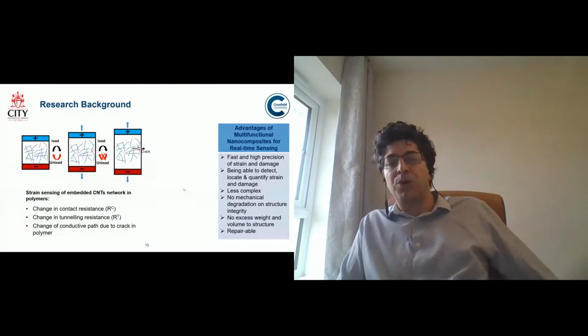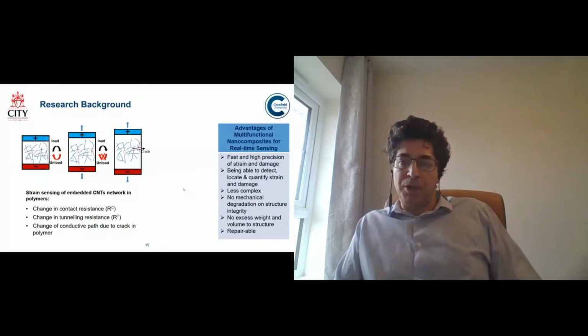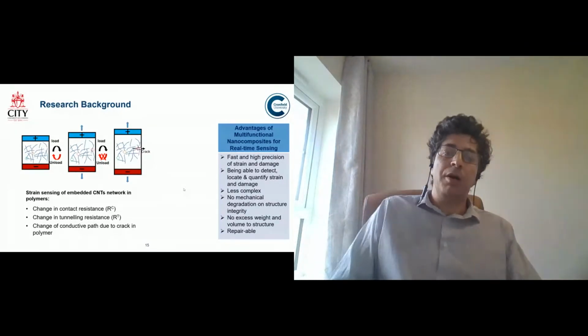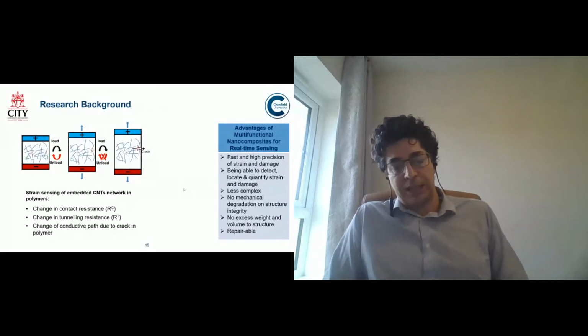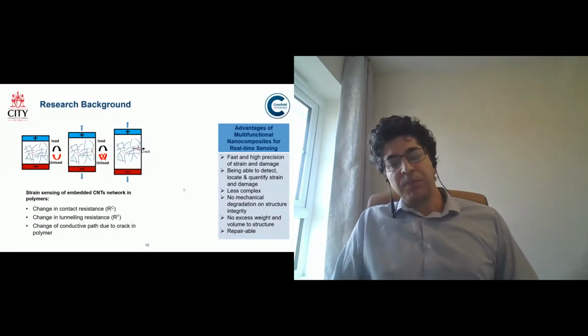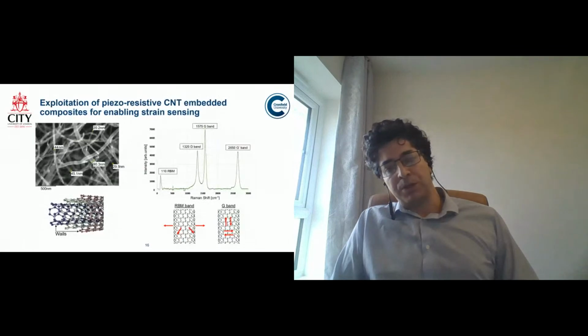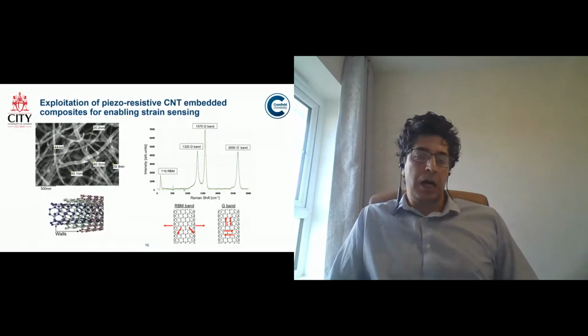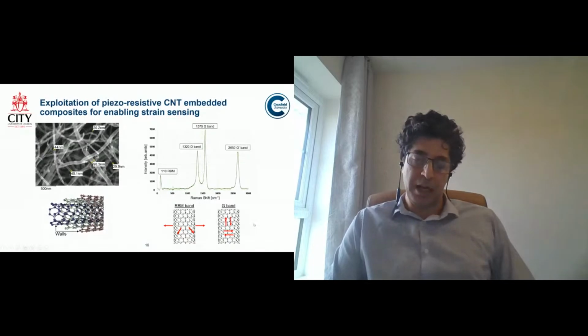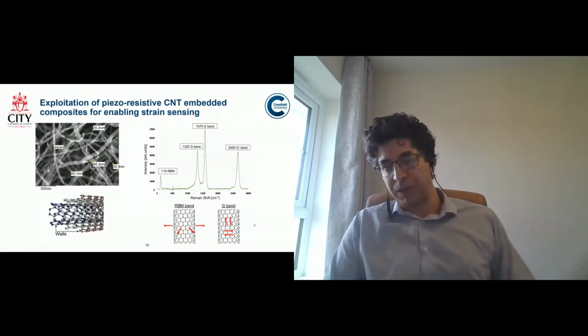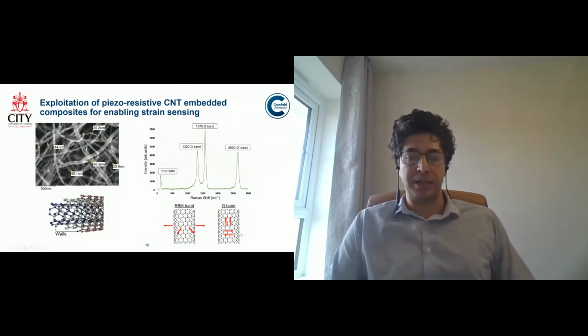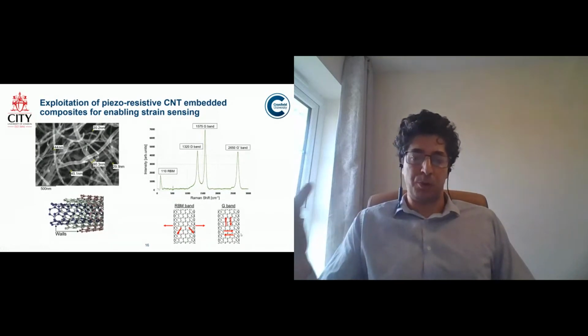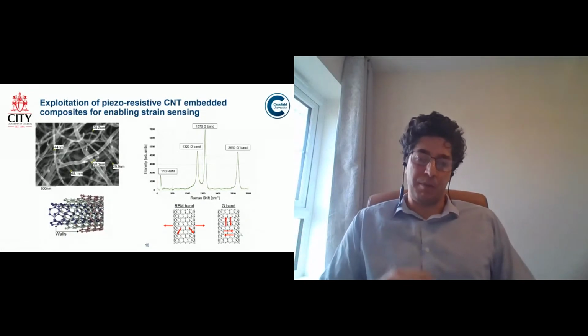We are actually specifically working on using carbon nanotubes to make multifunctional nanocomposites for smart sensing, because these materials are electrically conductive, and we rely upon their change in resistivity. That's the material we're talking about here, synthesized by chemical vapor deposition. These are hollow structures which are really, really low weight, and the aspect ratio, the length over the diameter, is about 10,000. It starts from 10,000 and goes up to multi-millions, if you make them in a very long shape.